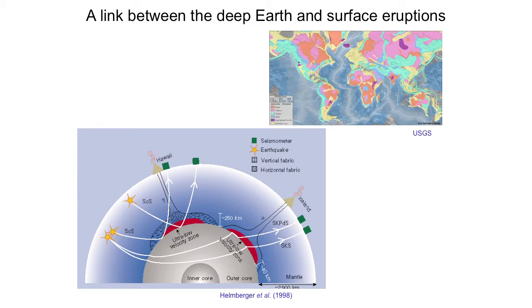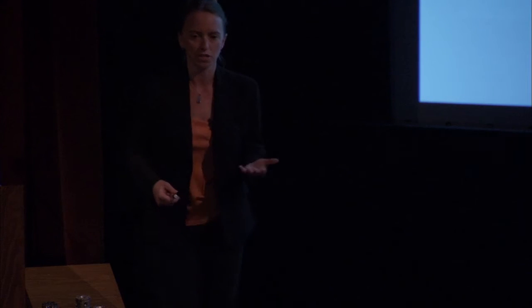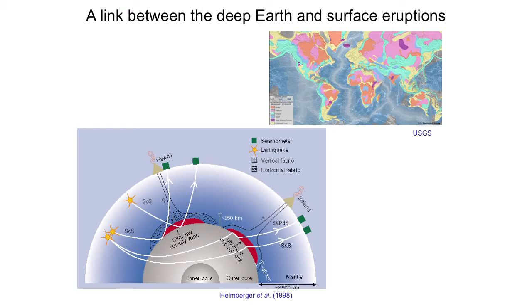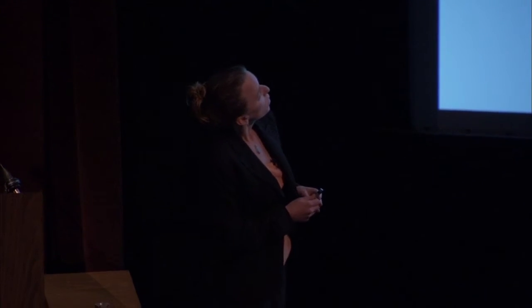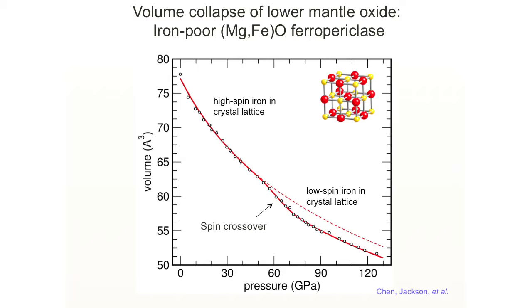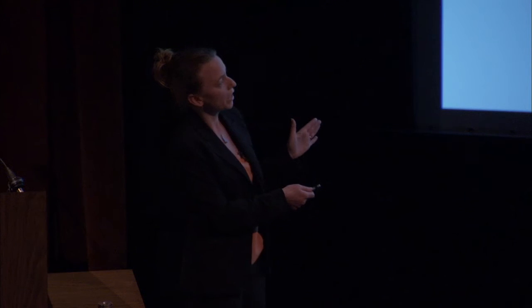And so understanding not only how materials behave at these pressures and temperatures, part of that understanding is the density of the material, or the volume. How does the volume change with pressure? And so here, buoyancy of materials, we want to ask that question, how will this material rise? Will any material rise? Especially if it's dense. So we've measured the volume. This is one of those features that we observed that was not observed about 10 years ago.